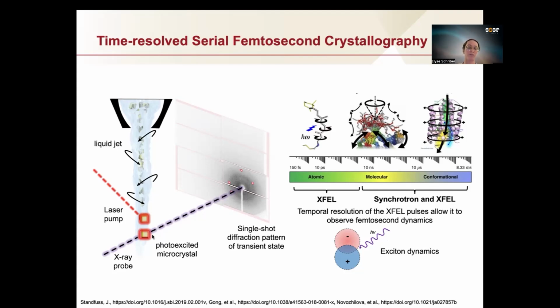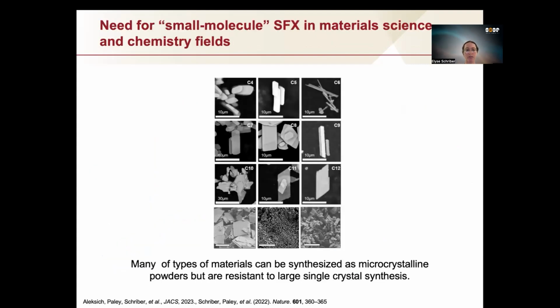And the way that it works is you use some kind of perturbation. In this case, it would be a laser pump. And then you have an X-ray probe. And the X-ray probe is so fast that it can actually capture almost a freeze frame of that photoactive state. And then you can start to collect all of that pump probe data and then compare it to a ground state structure. And it can tell you something about that excited state, where those atoms might be positioned, and more information about the transient process that occurs.